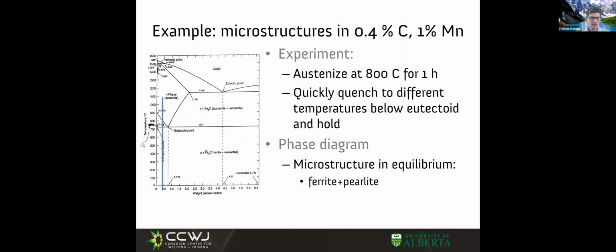The microstructure in equilibrium, in all cases, should be primary ferrite that came as we crossed this two-phase region, and then the austenite that comes, if you do the lever rule, when we are going down this line, just before the full transformation, we're gonna have some amount of ferrite at this composition and some amount of austenite at this composition. If you don't remember the lever rule very well, or don't remember very well how to operate with phase diagrams, take a quick look. This is very basic.